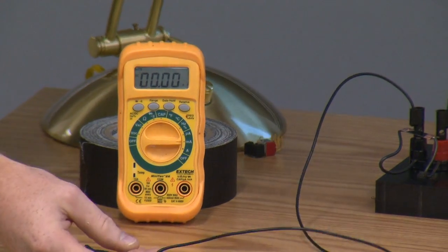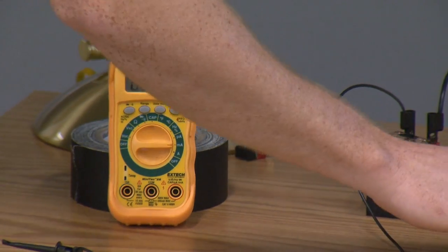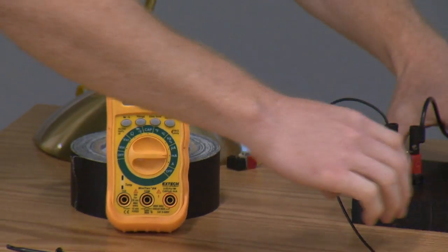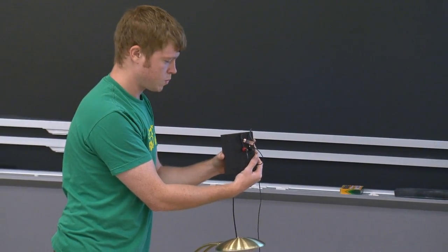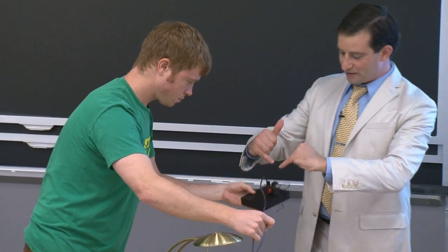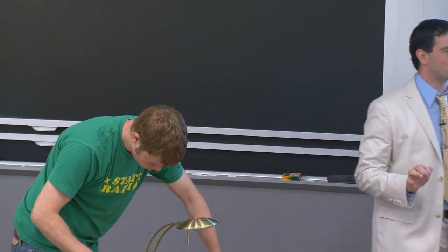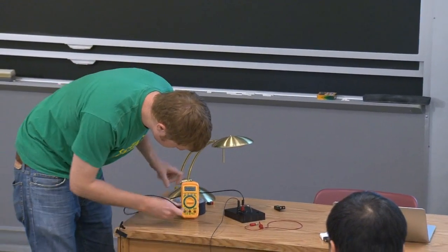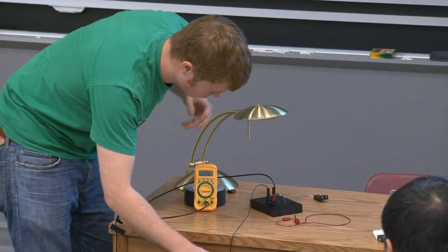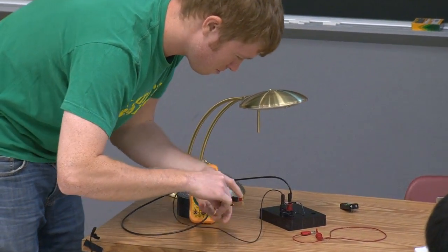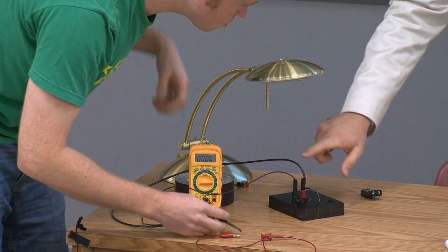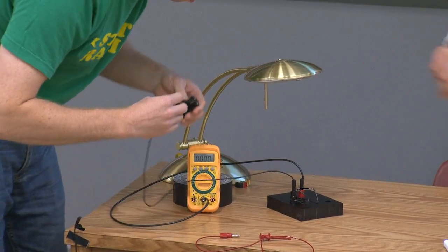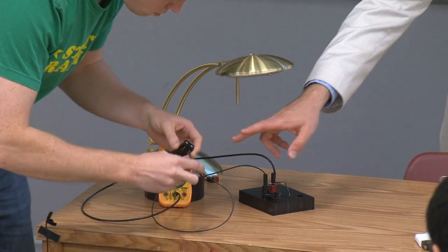Let me explain to you what we have right here. We have a bare piece of silicon and 2 electric leads on either side. So it's a bare piece of silicon, no device, just a piece of silicon. And we have electrical leads coming out of either side. We have a very low resistance contact on either end. For those who are curious, we used a mixture of indium and gallium, soldering iron, scratched the surface, penetrated the native surface oxide, and put the electrical leads on either side. And we have this connected in series here to our current readout device.